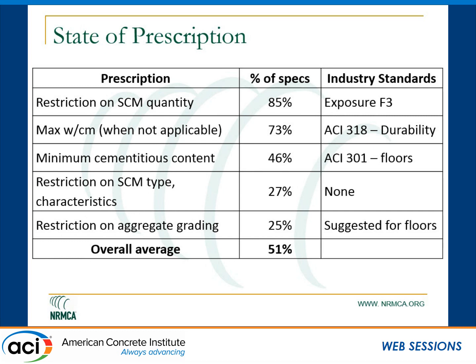That means you cannot use more than so much fly ash or slag in your concrete mixtures, was there in 85% of the specifications that we reviewed. Where do we have this in industry standards? In ACI, the only restriction that we have this in is when a member is designated or assigned to an exposure class F3, where it's going to be exposed to freezing and thawing exposure and the application of de-icing salts.